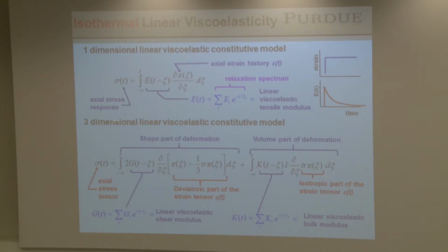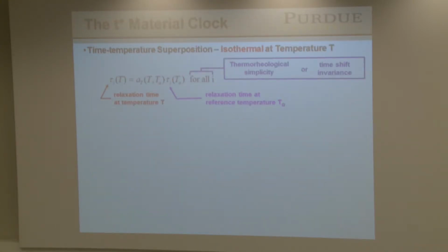That's in one dimension. When we go to 3 dimensions, it comes down in very, very similar form, okay? This is still our shear response, and that is the shape-changing part of the deformation. And over here is the bulk relaxation modulus, and that is the volume-changing part of the deformation. So all we've done is we've now had shape and volume change. Each one of them has its material relaxation function. That's the shear viscoelastic modulus, and here is the bulk viscoelastic modulus. So basic ideas up here, but we now have to do it in 3D.